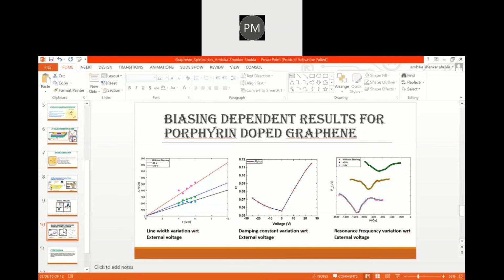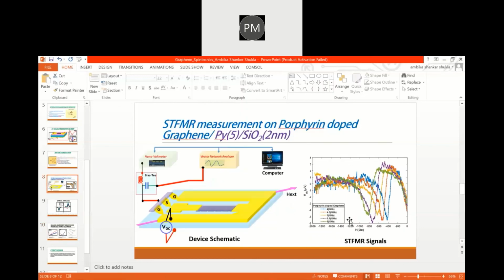Okay. Yes, sir. But this line width you have extracted is a very narrow frequency range, only 2 gigahertz. Is it because the signal goes down at high frequency, or what is the reason? So no, up to 6 gigahertz we have obtained. You can see in this we have gone through some 6 to 6.5 gigahertz. So the STFMR spectra, here I'm showing till 6 gigahertz. We can easily see this signal up to 6 gigahertz, but then it goes down if you go to 7 to 8 gigahertz.